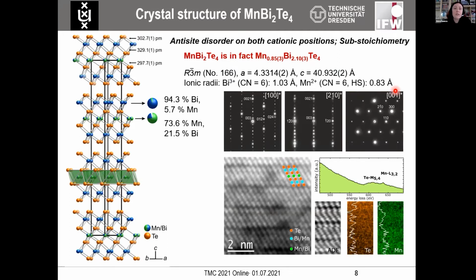So when we looked at the obtained crystals of 1-2-4 phase by single crystal X-ray diffraction, we noticed that there is always intermixing disorder, antisite disorder in this phase. So this position is not purely manganese and this position is not purely bismuth, but it has some intermixing with the other cation. So you have some bismuth on the manganese place in the central position and some manganese on the bismuth place in the outer position of the septuple layer.